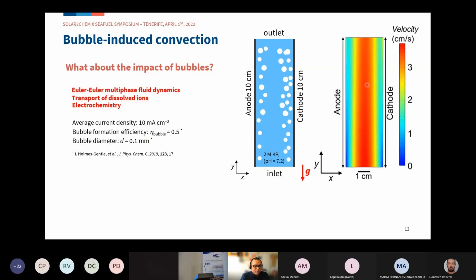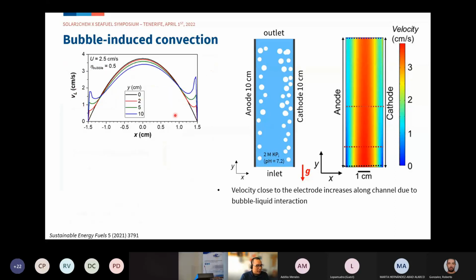This is the color map of the velocity profile from the inlet to the outlet. If you notice, the velocity of the electrolyte close to the electrode increases along the channel of the cell. This is clearer if we take a profile along the y-axis, shown here: going from the entrance at y=0, we see a typical parabolic laminar profile, and along the electrodes we see an increase of velocity due to this bubble-liquid interaction.